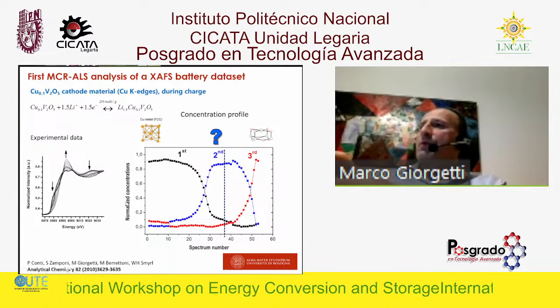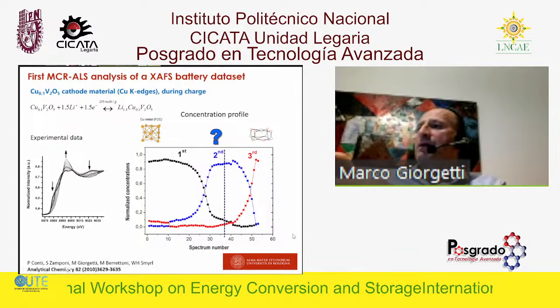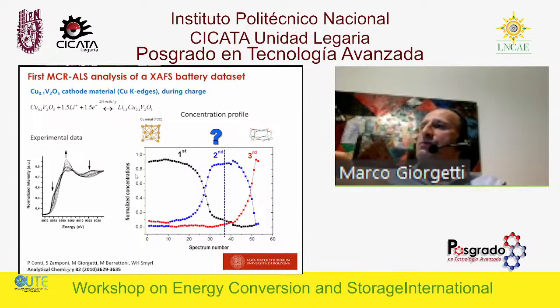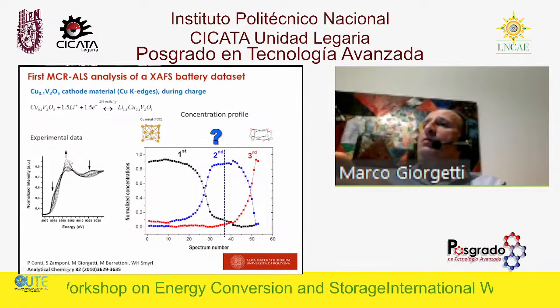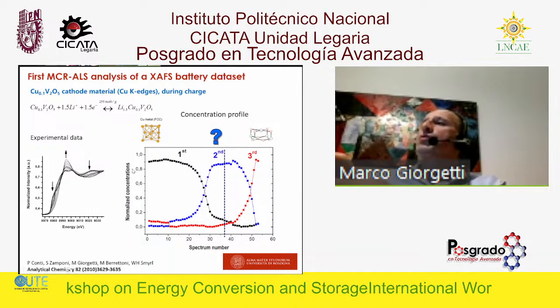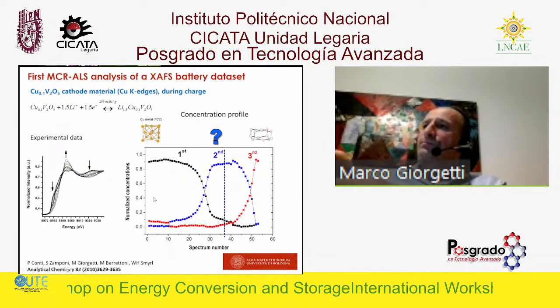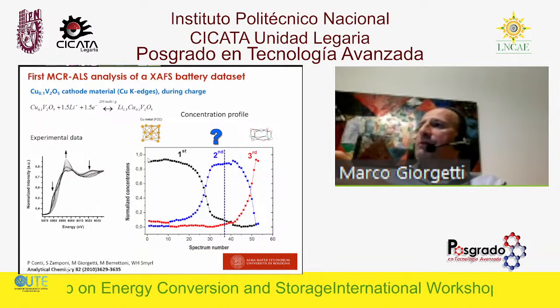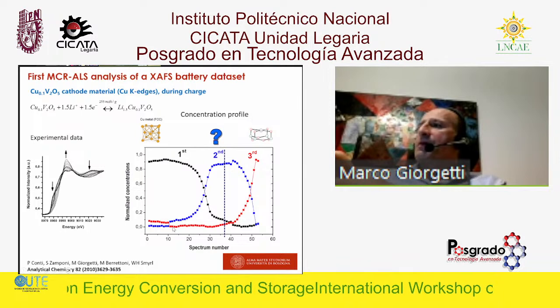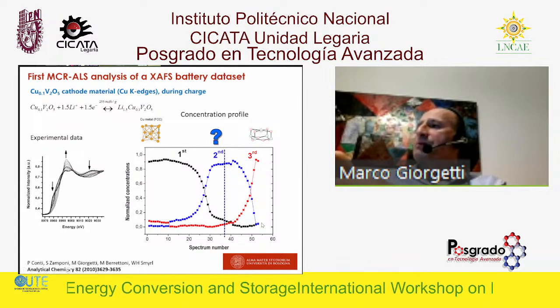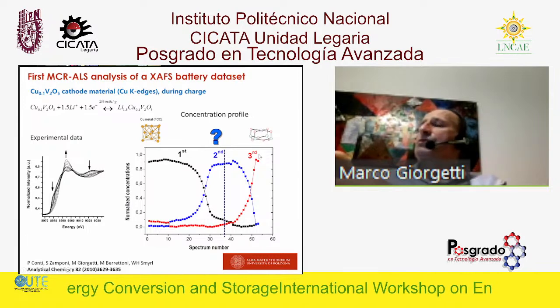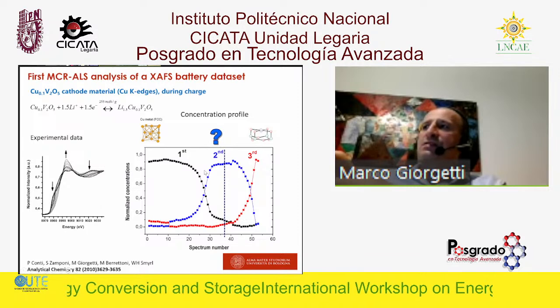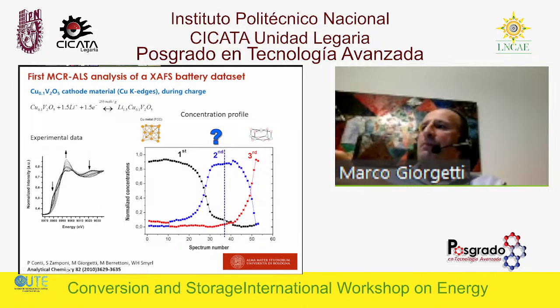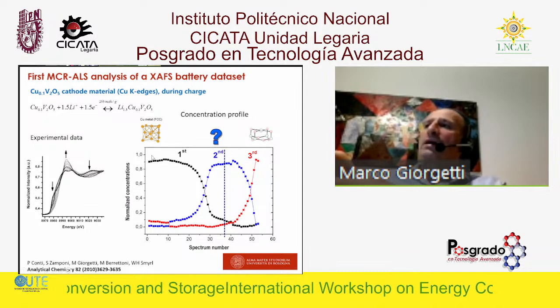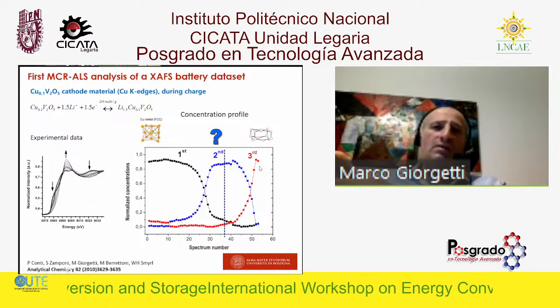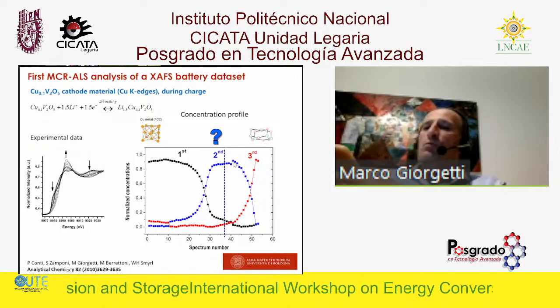Basically, what we got here, if you consider the full data set, is the concentration profile, as indicated. Of course, you have the spectrum number as the axis for the concentrations. And we were able to see that this data set comprises 3 types of pure spectra. The first one is long-lived. Then the second one pops up and then goes down. Then we have the third one. So basically, we were able to identify the transition state by fully charging the batteries. You not only have phase 1, the initial one, transforming to phase 3, but we were also able to see a second phase that was long-living.